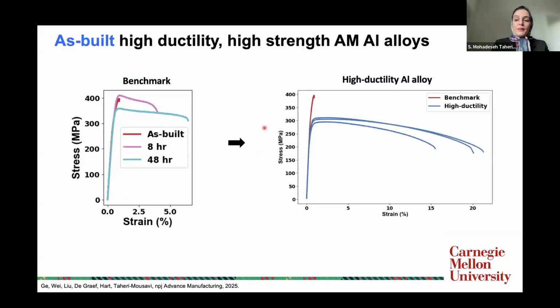We further improved the properties of this alloy because we had a lot of industry interest. The as-built ductility of this alloy when you do a tensile test was very limited. And this is very important if you really want to print larger scale parts of this alloy.